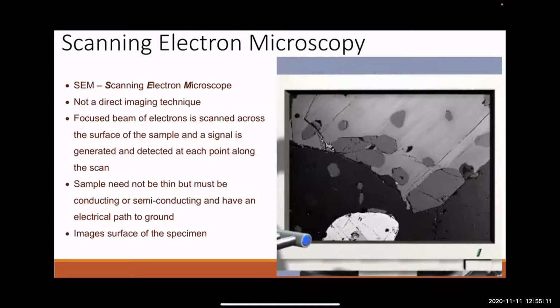And so the solution, often or typically, is just to put a very, very thin, and by thin I mean maybe a few nanometers, layer of a metal on top of whatever your insulating structure is. And that usually is good enough. Maybe it doesn't eliminate the charging, which is the number one artifact you see in SEM, but mitigates it to the point where you can take reasonable images.